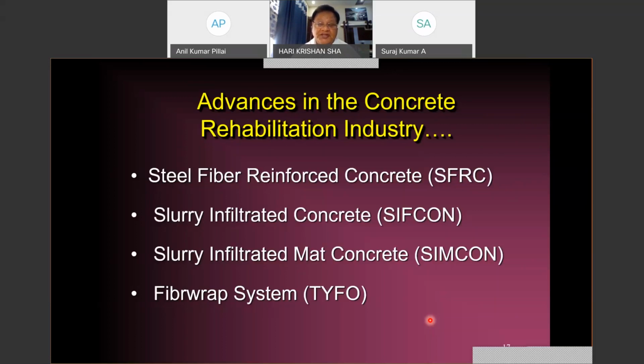So this was a change in the construction industry around 2005, and in 2013 we applied for a patent and got a patent on this material, along with its application in civil engineering structures for retrofitting. Then came into existence the fiber wrap system. This SIMCON, because of the large fiber volume content, was not found economical at a later stage. Many industries did not manufacture these long fibers. They confined themselves to the production of only small length fibers. So we had some problem in procuring fibers of longer length and small diameter.